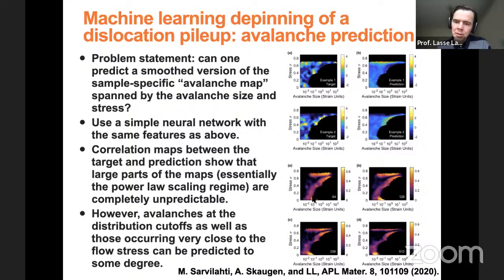But the funny thing is that there is some positive correlation here and here, which basically means that avalanches in the cutoff are generally to some extent predictable. And also, finally, avalanches very close to the flow stress, even if not in the cutoff only, are also to some extent predictable. This is a funny thing, which would be nice to understand better. But it seems that whenever you are not exactly at the power law part of your avalanche distribution, then you can predict at least something. So the largest events that you get at a given stress level, those you can predict with some accuracy. Not perfectly, but a little bit.